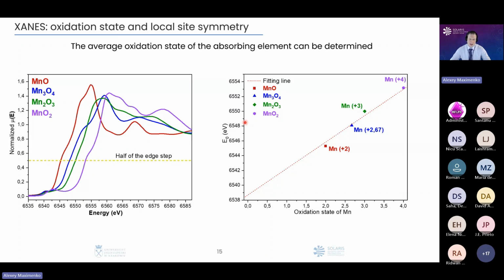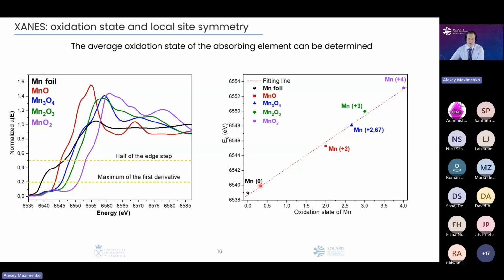For example, you define the position of the absorption edge as half of the edge step, and then you put it onto this straight line, and you could easily understand what the oxidation state is. Sometimes you will tell me that it is quite hard to make such a line, but you can also use compounds with a zero oxidation state, for example, a metal foil. But in this case, be careful. You will need to use the maximum of the first derivative in order to make this line.